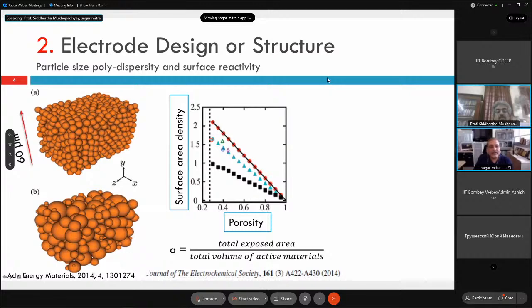have it without non-uniformities, all uniform, same size, same shape, what we predicted is that the surface reactivity enhances 2 times. So that is another angle. If I make these particles all the same size and shape, I may increase the surface reactivity 2 times. This is a theoretical prediction. There is a possibility that I can enhance it further with the same electrode, same materials. Don't have to do further, but this is challenging.